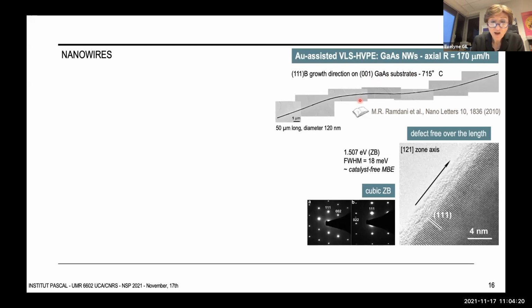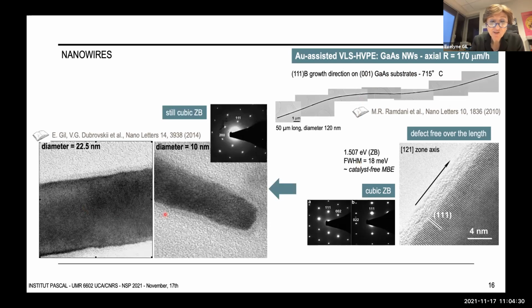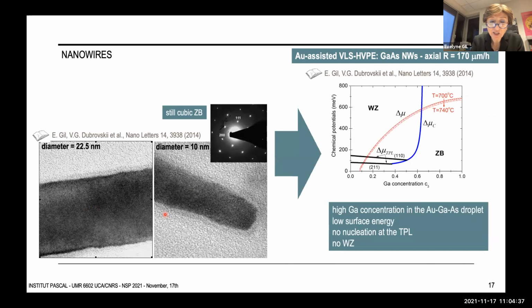The main property of these nanowires is that they are defect-free all along the length of the nanowires, and then they remain cubic even for small diameters when they are supposed to experience polytypism. This was explained by Vladimir Dubrovskii and Frank Glas by comparing the chemical potential of gallium arsenide in the liquid droplet and the critical chemical potential for nucleation at the triple phase line, which is supposed to give the wurtzite phase, and at the center, which gives the zinc blende phase. So as you can see, once the gallium concentration in the droplet is 60%, the cubic phase should be dominant.